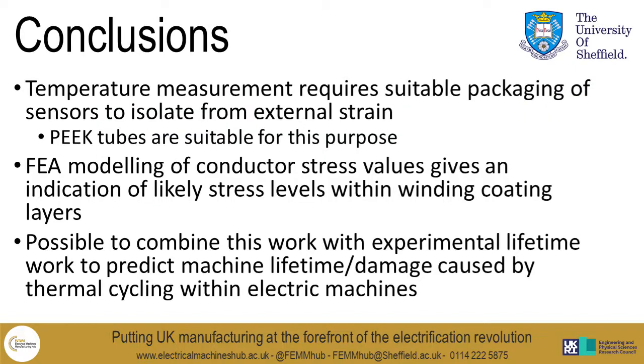So to conclude this presentation, firstly, we've demonstrated the use of FBGs for measuring temperatures. We've shown that isolation from external strain is required and demonstrated that a PEEK tube is a suitable material for this purpose. We've also shown that FE modelling of conductor stress gives a reasonable indication of the likely stress within the winding coating layers. And finally, we've also shown that this work can be combined with experimental lifetime work to predict machine lifetime or damage caused by thermal cycling within electric machines.